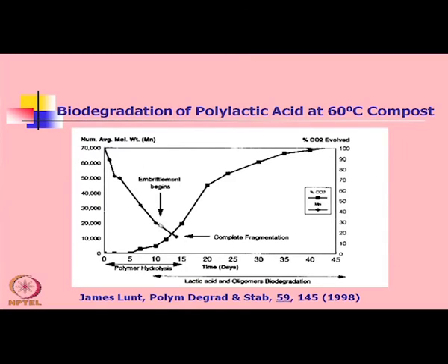Now, within 10 days time, embrittlement of the polymer to fragmentation starts, and after 15 days it has been found that the polylactic acid was completely fragmented at 60 degrees Celsius in compost condition.